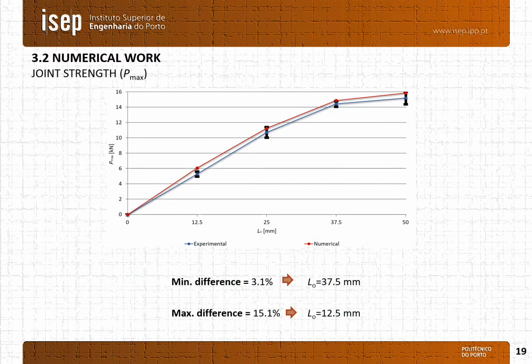Comparing the numerical results with the experimental ones it is possible to see a satisfactory agreement, being the minimum difference 3.1% for an overlap length of 37.5 mm and the maximum difference 15.1% for an overlap length of 12.5.